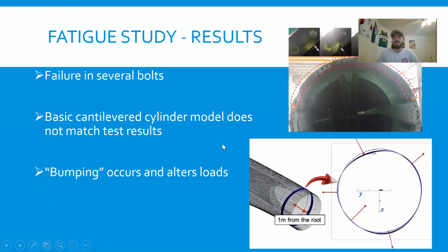So then what ended up happening? Well, from the physical test, several bolts failed. However, there was not catastrophic failure with the blade thrown. However, these bolts were elongated, some of them bent, unable to carry the loads, but still the connection was tight enough to keep the blade attached. There's just some joint separation at certain locations.